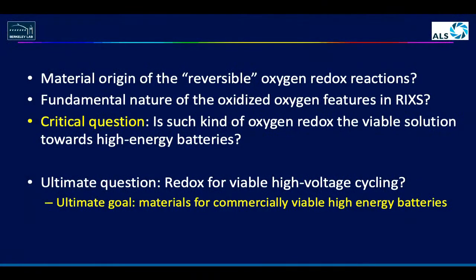So with that said, let's just look at the observation itself. It seems like we get some good sense of a sort of reversible oxygen redox when you cycle the oxide into the very high voltage regime. However, although some material shows much better reversibility and some shows worse reversibility, the one even with the better reversibility shows another issue called voltage hysteresis. So it could be thermodynamic, it could be kinetic issues. None of those seems to be really commercially viable, honestly speaking.